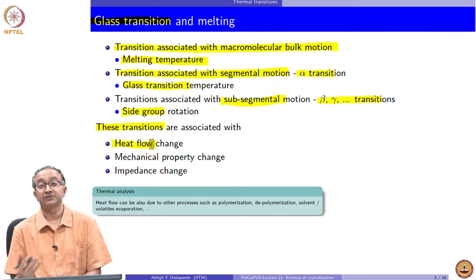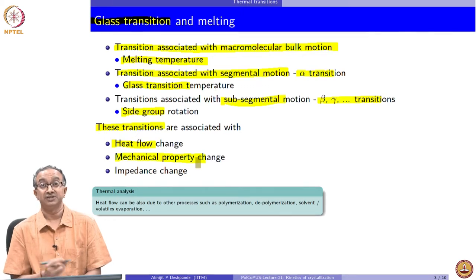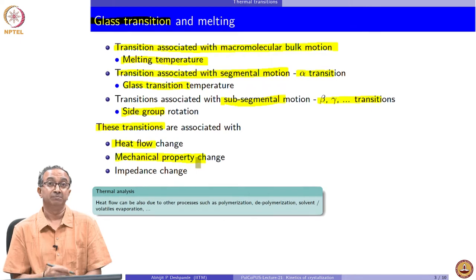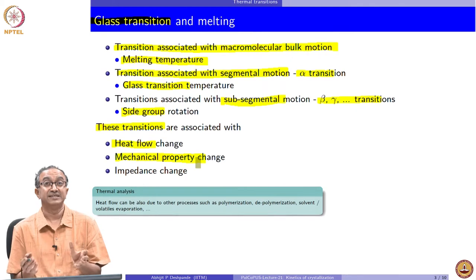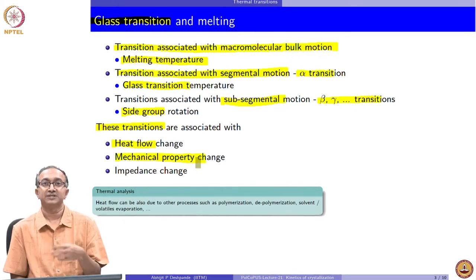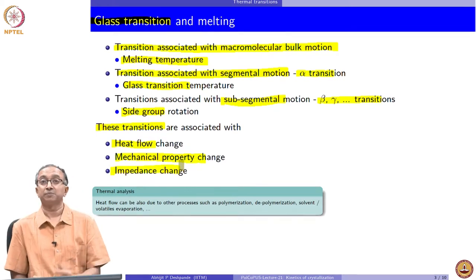These transitions are important from an application point of view: if we are trying to use a polymer in some application, we need to know how much the properties change. For example, a mechanical property can change by three orders of magnitude across a glass transition — if the modulus is in gigapascals below glass transition, it can become megapascals above glass transition. Similarly, diffusion of small molecules in polymers can also change.